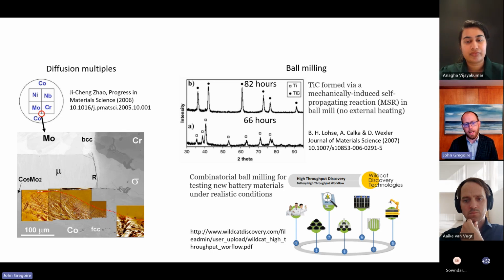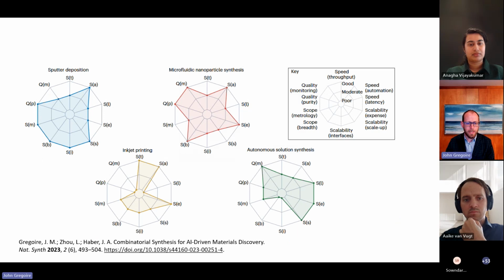It's one of my favorite examples when people ask, why is synthesis hard? Why can't we just predict what happens? This is titanium and graphite in a ball mill. After 66 hours of ball milling, all you see is the titanium, the reactant. After 82 hours, something magical happened and it all transformed to phase pure titanium carbide. And I don't know of any algorithms that were going to predict that that was going to happen. So synthesis as a broad landscape, especially in bulk form, can be very time consuming, and in all forms is very hard to predict.